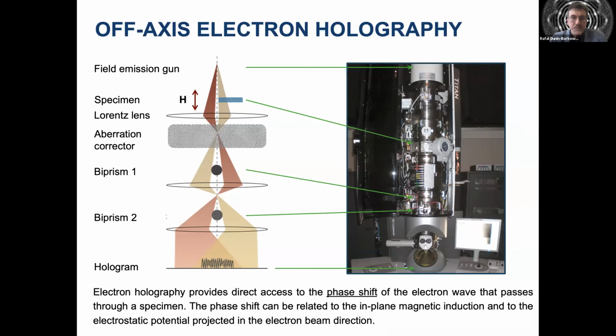For imaging magnetic materials, as I mentioned, the sample is located in magnetic field-free conditions, and then an external magnetic field is usually applied using the vertical field of the objective lens, and then the sample can be tilted in that field. So the phase shift is important because it provides access to the projected electrostatic potential or the in-plane magnetic field B projected in the electron beam direction. And today we're focusing on the magnetic field.